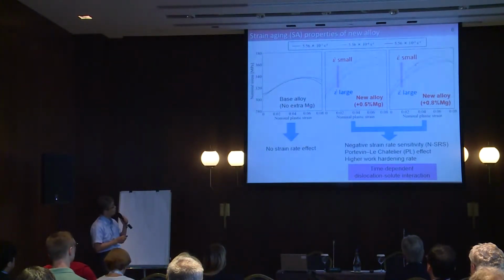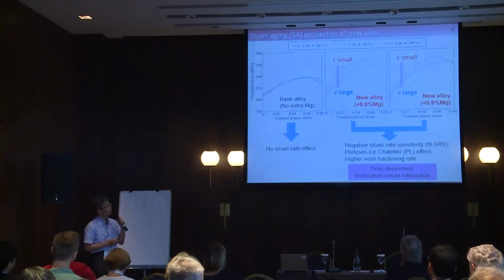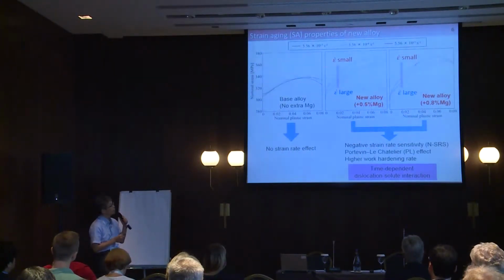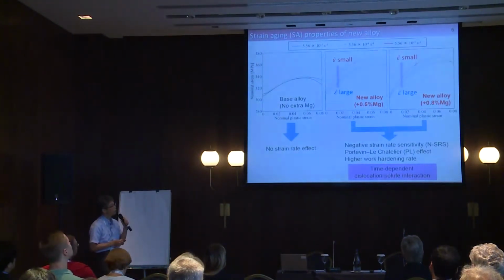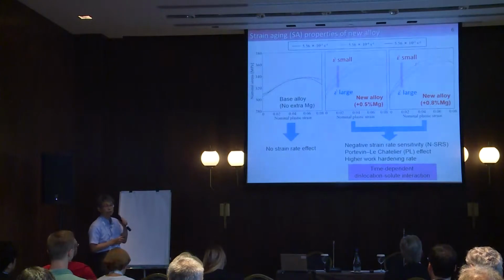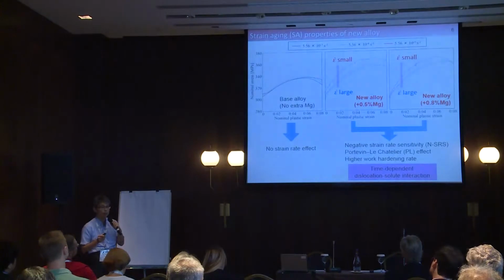The base alloy does not show any strain rate effect. Here, the tensile tests were done under 3 orders of different strain rates, and no strain rate effect is observed. But for new alloys, containing plus 0.5 and plus 0.8 magnesium, they show higher strengths. For example, the flow stress becomes higher at lower strain rate. This is completely the opposite behavior compared to the normal alloy.